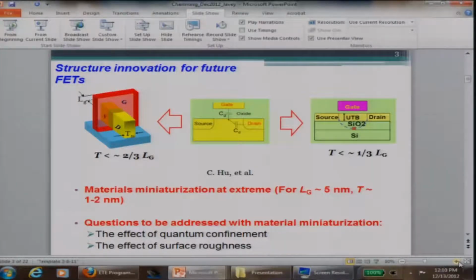The other structure that was proposed is the ultra-thin body SOI, and the idea here is similar, that you are cutting off the silicon that is far away from the gate and replacing it with a silicon dioxide, an insulator, and by doing that, you reduce your leakage paths. And this is a nice rule of thumb that you can use for the scaling limits. The thickness of the fin that you need to get good electrostatics is going to be roughly 2/3 of the gate length. This is for silicon. And for an ultra-thin body device, it's going to be roughly 1/3 of the gate length.